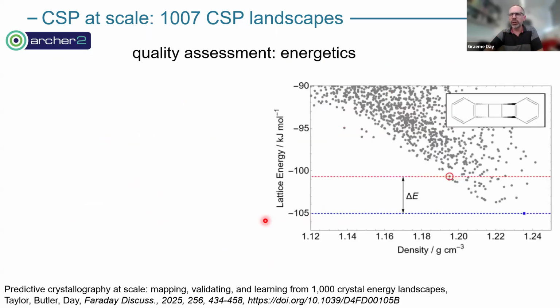Okay. We wanted to look at the quality of the database that we've got. So one thing, going back to that assumption, is are the observed structures near the global energy minimum on the landscape? So we looked at this quantity delta E, which is looking for a match to the experimentally observed crystal structure for each particular molecule, and then how far above it is from the global energy minimum. We're expecting that if the energy model we've used for the predictions is working well, this distribution should be close to 0. Okay, where delta E is 0, that's where our predicted structures are the global minimum.